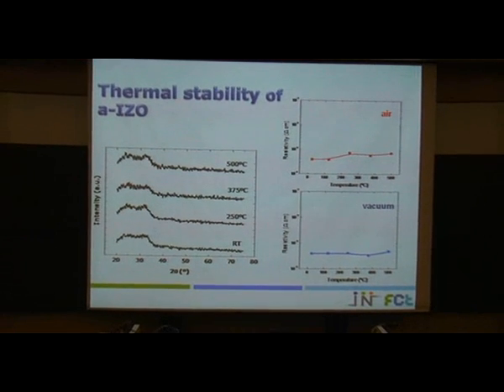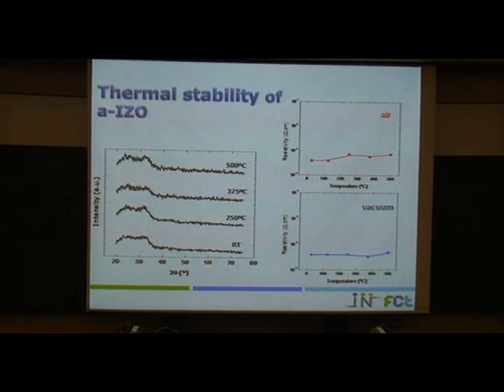We perform some thermal tests just to see the stability. And even, for example, the material as produced at room temperature is amorphous, but even at 500 degrees, the structure is the same, amorphous. And this is the resistivity measured in air and in vacuum, and it is also the same depending on the temperature. This means that the material is quite stable.